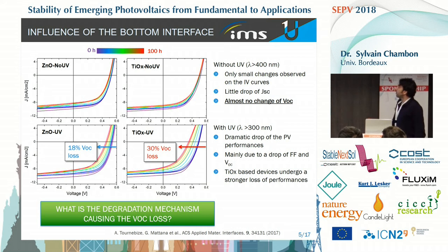As you can see, when you cut the UV, in both kinds of devices, zinc oxide-based or titanium oxide-based, you have some degradation, but you don't have any or only a very small change of VOC. But as soon as you have some UV present during the aging condition, we observed a drop of the VOC. What was also very interesting was to observe that this loss of VOC was stronger in the case of titanium-based devices.